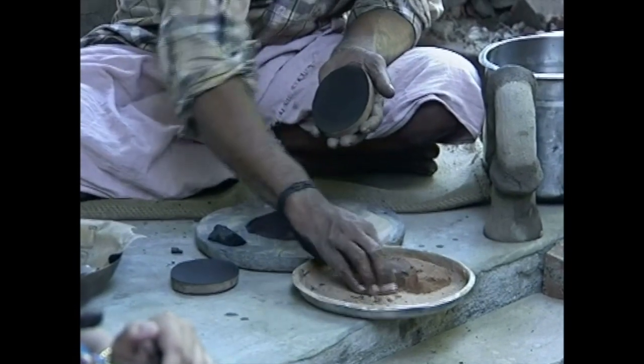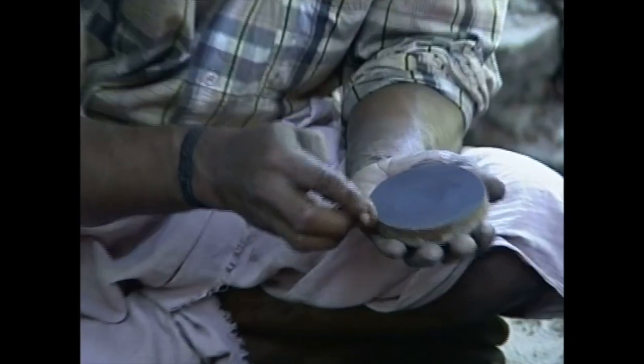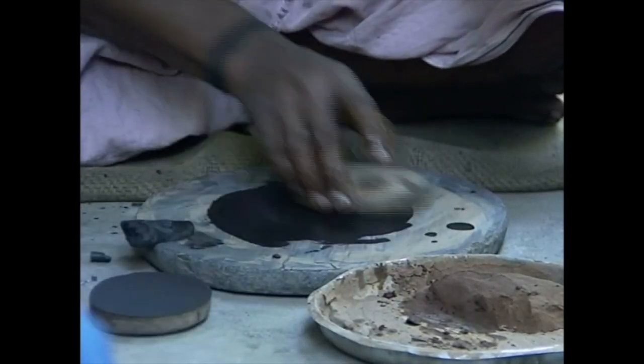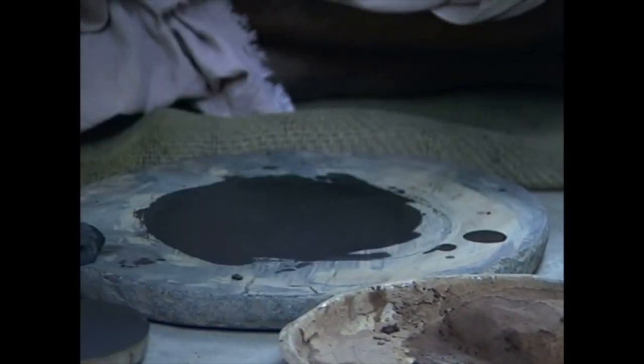That is on the side he puts the pottery, the powder made of pottery is on the side. So you see it's a very fine slip which is applied on the surface of the mold. And using charcoal makes sense because charcoal will absorb the gases so that you get a very fine blank for the mirror, which is absolutely flawless.